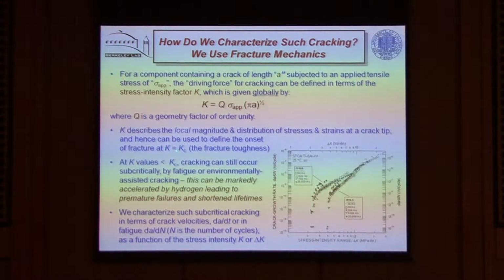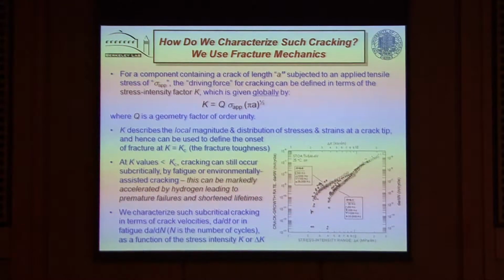Now, in its simplest form, we talk about a critical value of K, which is known as the fracture toughness. That's when the component breaks in two or whatever. It's the catastrophic failure point. But that's simply the end point. If one wants to know how long a component may last, a hydrogen tank, a pressure vessel, a piping, one needs to know how long it takes any pre-existing crack, which inevitably will be there, to grow until you exceed this fracture toughness. And that's what subcritical crack growth is, and that's the essence of the prediction of life in most engineering components. And so we talk about when K values are less than K critical, cracking can occur subcritically.